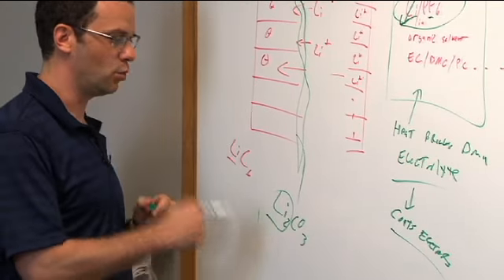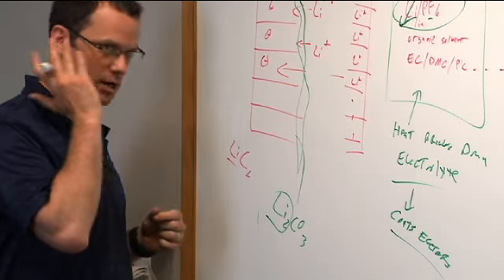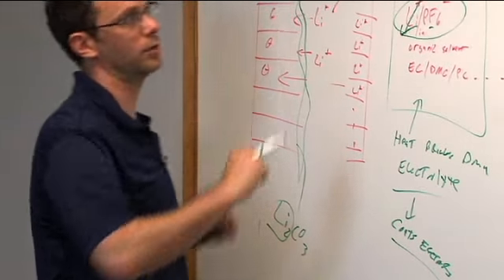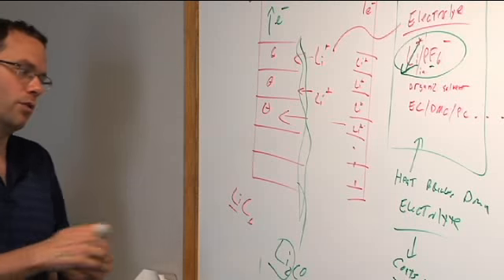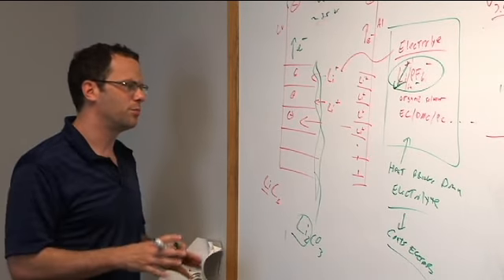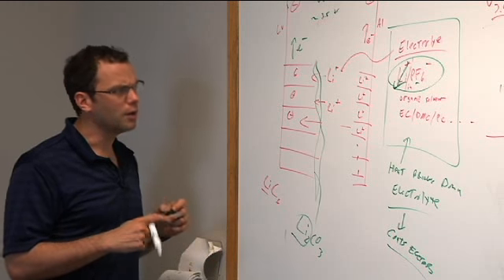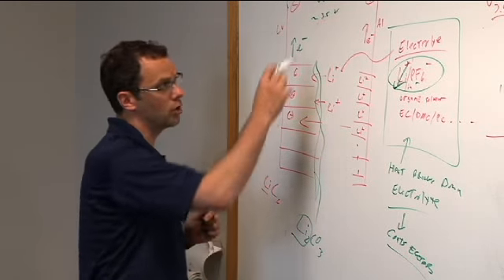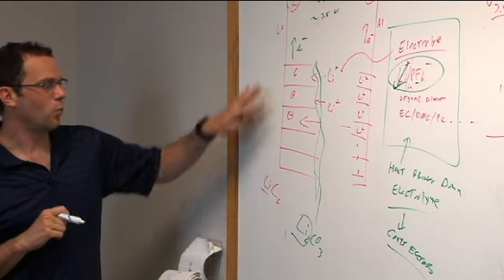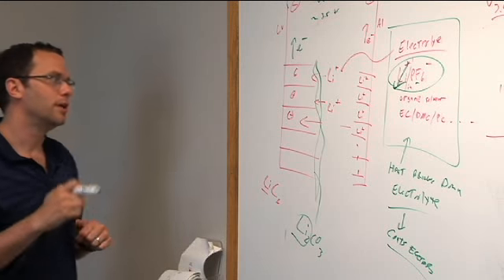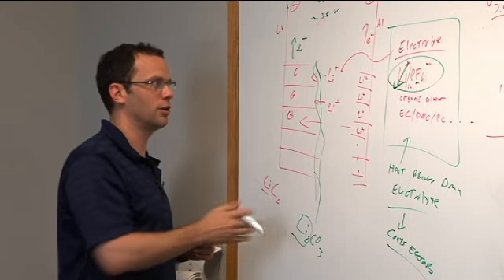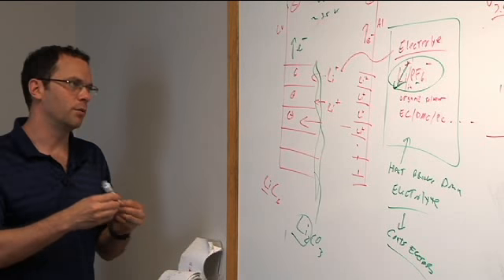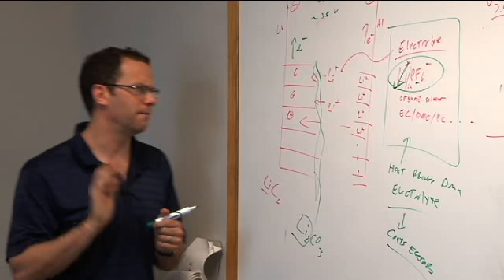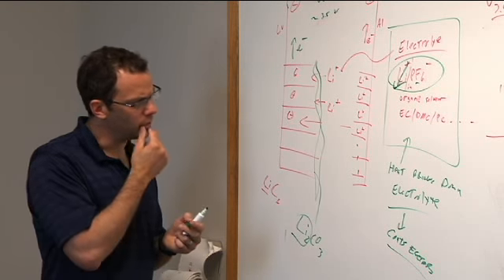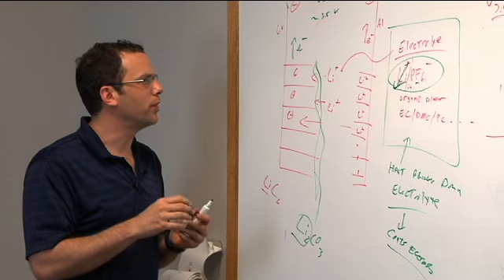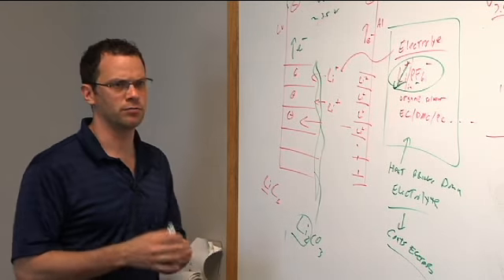And this decomposition happens more rapidly if you expose your batteries to high temperature conditions, because it's a thermally motivated kinetic decomposition, right? And so what you want is, and now there's so much proprietary activity these days in the battery world, but there are additives to put in your electrolyte to make it better. There are special coatings. One of the most interesting things is that how fast this decomposition happens in part depends on what the decomposition surface looks like to start with. And when I was at JPL, we were working with A123 Systems right after they got founded, in 2004, 2005, 2003 even, I'm not sure. We were giving them some of our low temperature electrolytes that we were putting on the Mars rovers and so forth.